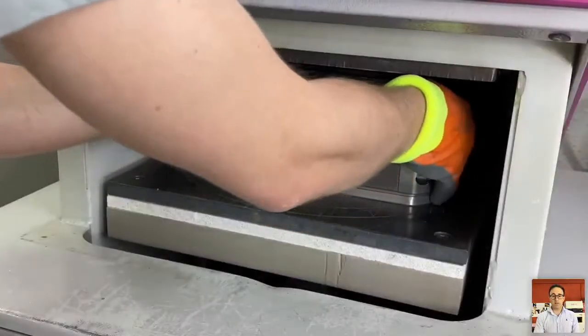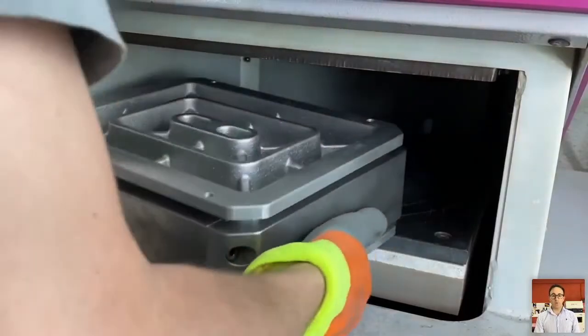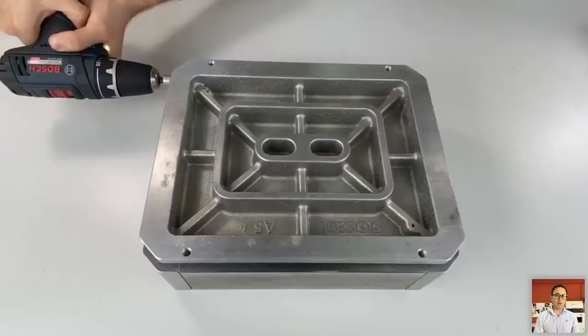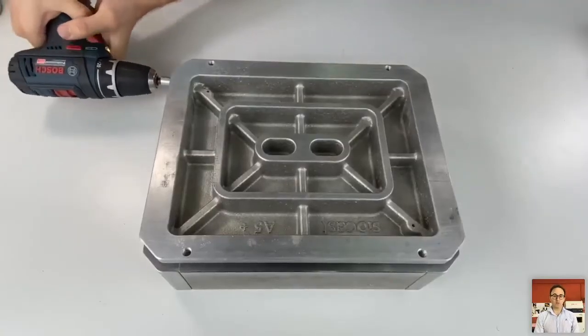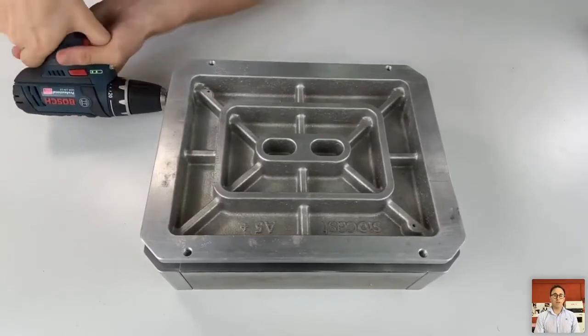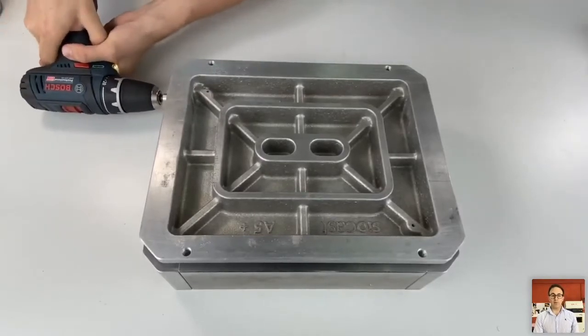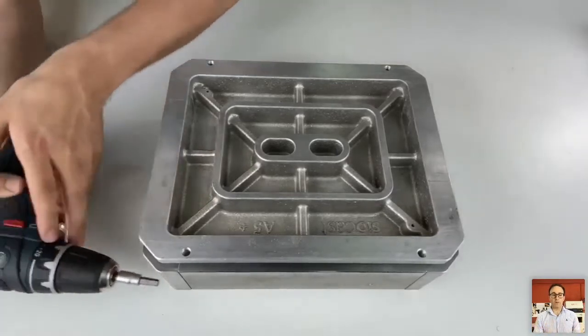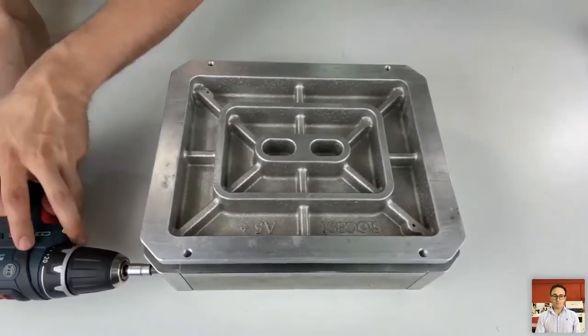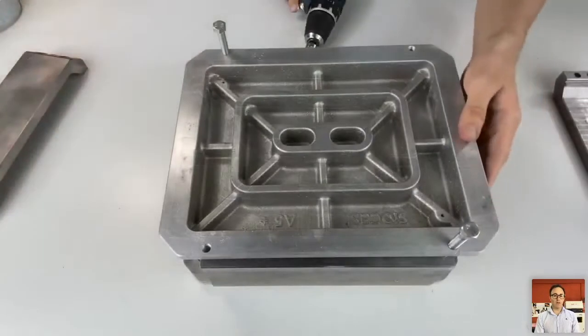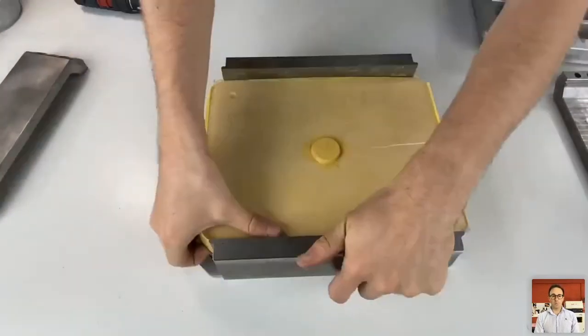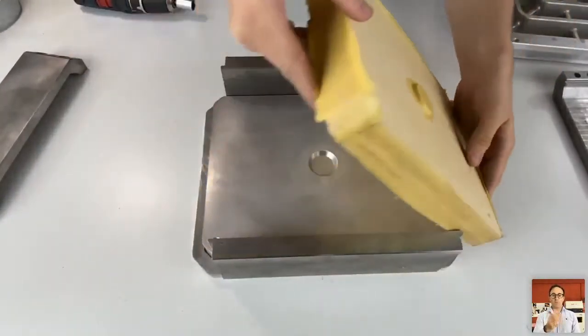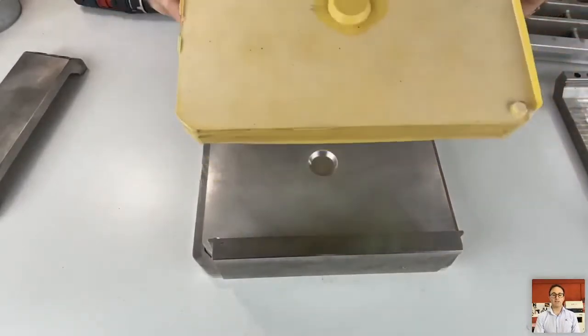This vulcanizing press is standard equipment on the market. What we are cooking here, the mold, will take more or less 1 hour at 120 degrees Celsius. When the process is done, we let the mold frame cool down, because if not, it's too hot, we open the mold with the tool. We remove the frame, and then we already have the mold vulcanized.